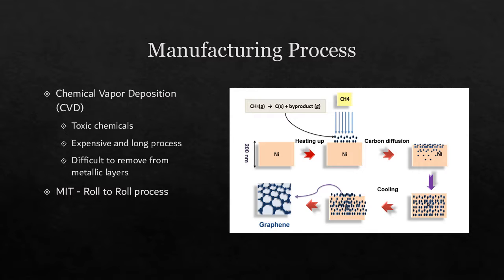The newest development in the graphene manufacturing process comes out of MIT: the roll-to-roll process. Essentially, this is the same CVD process as before, except the copper sheet starts on one roll on one end of the machine and then is robotically sent through the machine at a specific feed rate to produce the desired size of graphene sheets. On the exit, it is then re-rolled onto a new roll to be taken and the graphene removed from the metal sheets. With this process, it allows manufacturers to produce much higher quantities and qualities of graphene.